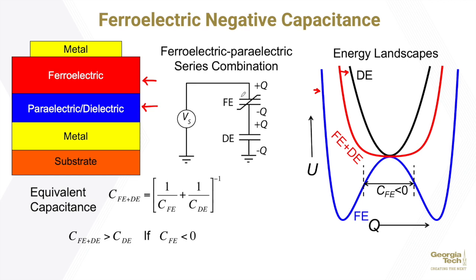Now again, since both the ferroelectric and the paraelectric materials are in series, both of them will have the same amount of charge across them. So to minimize the energy, the total charge of this heterostructure will lie in the minima of this red curve over here, and that will also correspond to the fact that the polarization of the ferroelectric material will also sit on top of this energy barrier, meaning that the ferroelectric will be in the negative capacitance state.